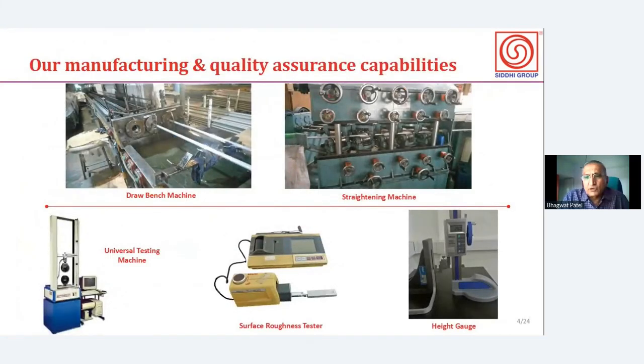Now, coming to our manufacturing capability, as I explained, we are manufacturing precision aluminium tubes, and today we are focusing on aluminium precision drawn tubes used for the manufacturing of waveguide. Basically, our process is that we purchase aluminium extruded tubes from our suppliers as per the customer's alloy requirement. The extruded tubes are then cold drawn with the help of cold drawing machines, which we call a draw bench, using different dies and mandrels as per the size required by the customer.